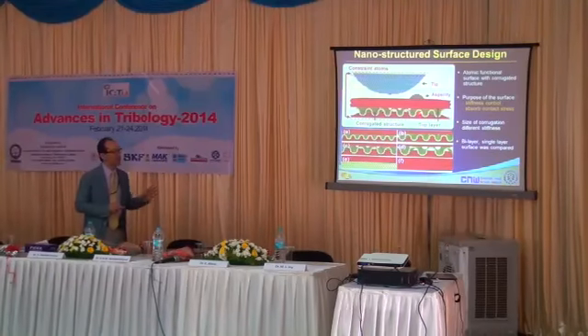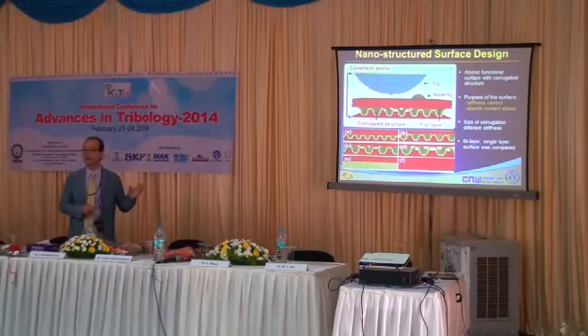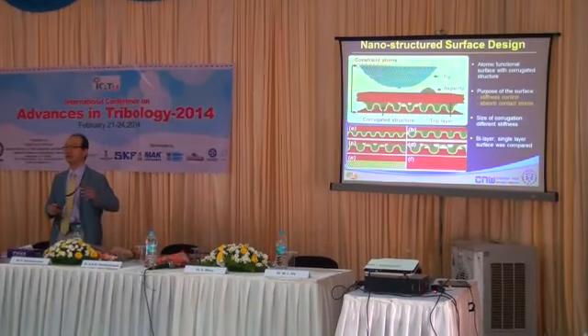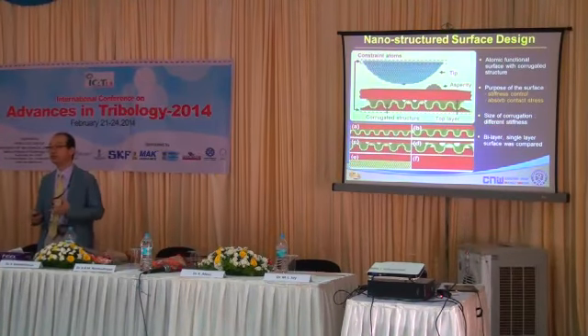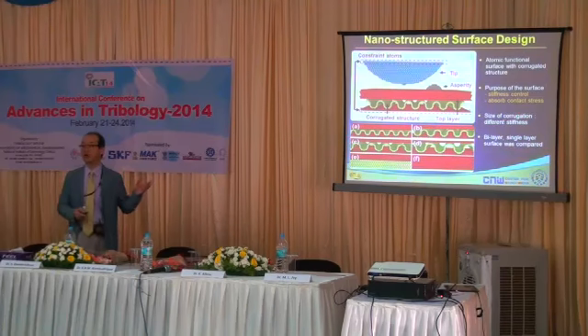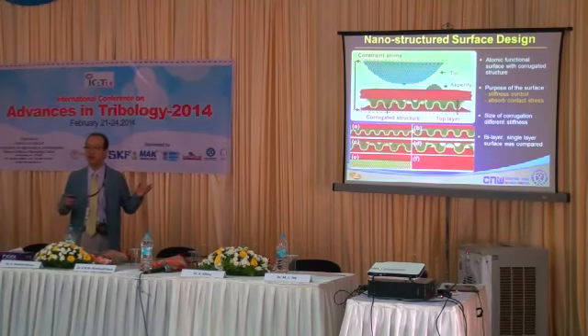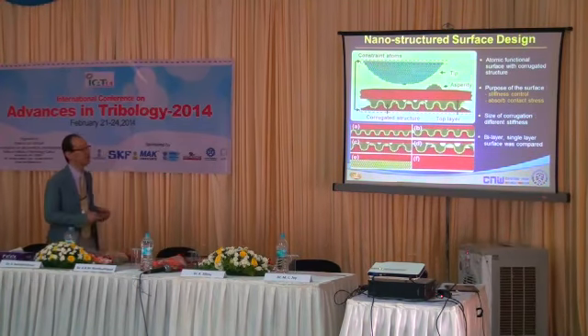So how do we make the surface so that it can absorb energy through large elastic strain, thereby dissipating the energy properly and not utilizing that energy to destroy the surface? We propose this kind of a surface. Basically, it's a corrugated surface. And if I were to force this type of surface into a realistic situation, this would represent what we call a folded graphene, a layer of carbon that's been folded that chemists work with.